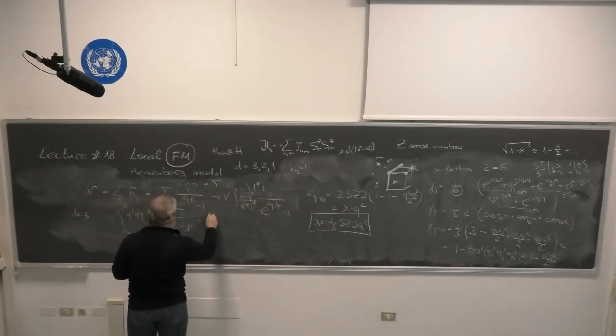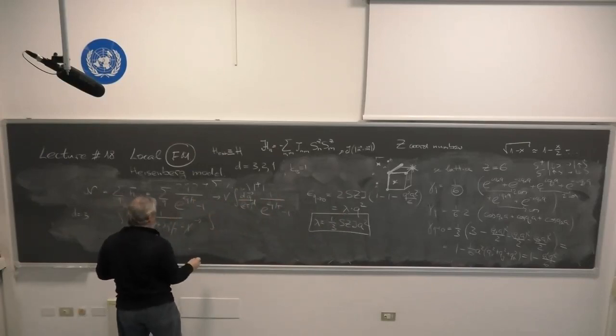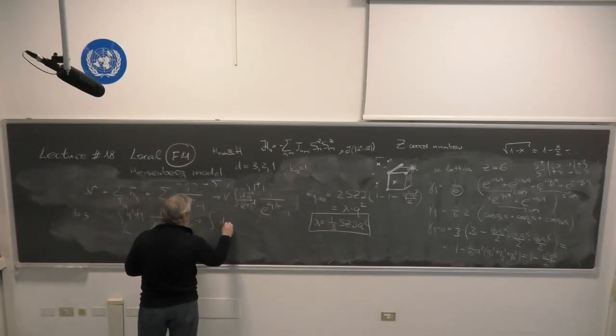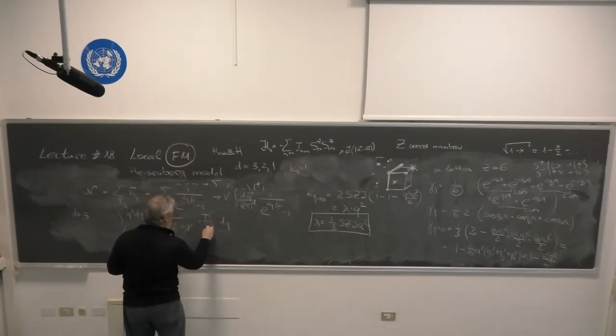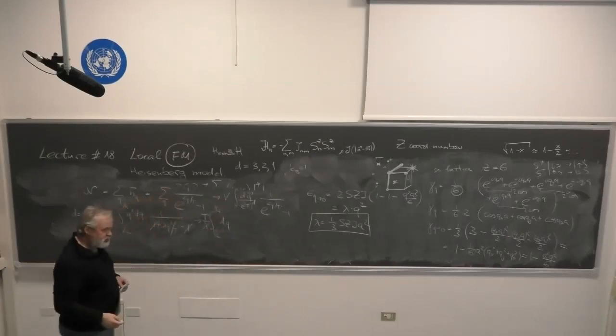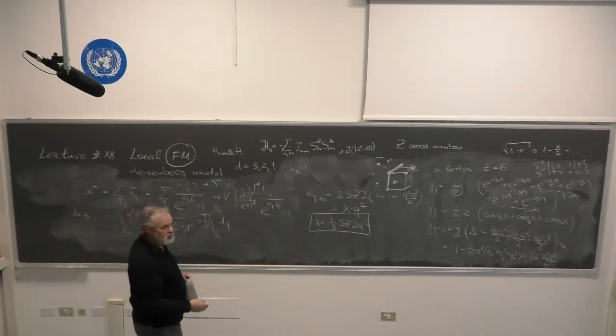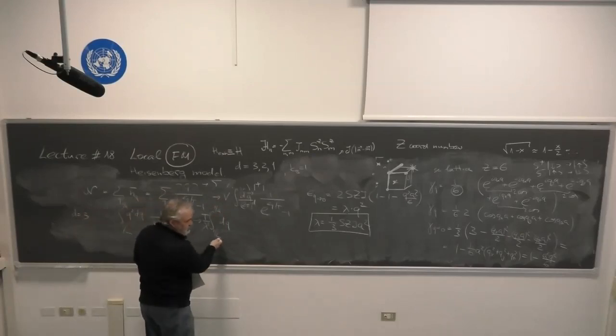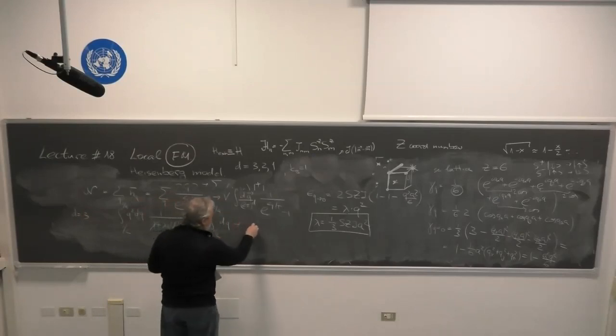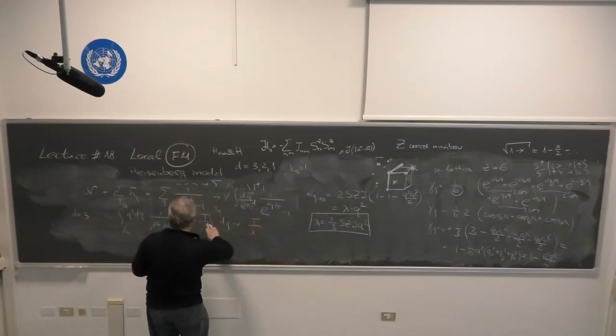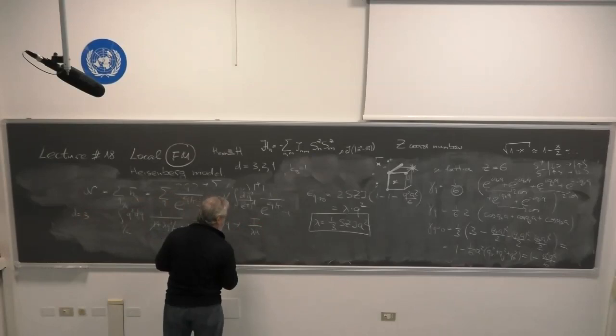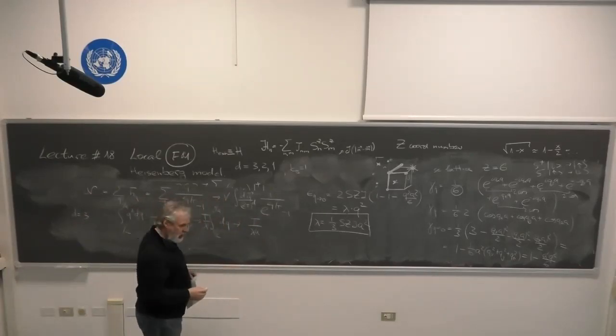Therefore, this is integral dq temperature over lambda squared from 1 over L to 1 over A. So you see that this integral is not sensitive to the infrared limit. I can take L equal to infinity, and therefore it will give me T divided by lambda, sorry, not lambda squared, lambda A. Okay? So in 3 dimensions, everything is okay.